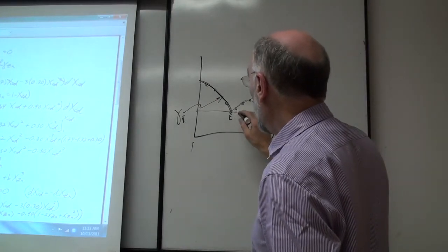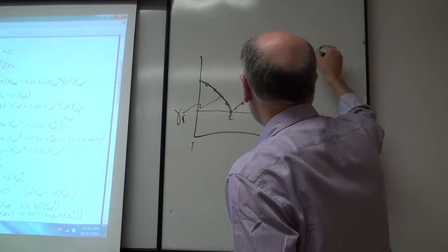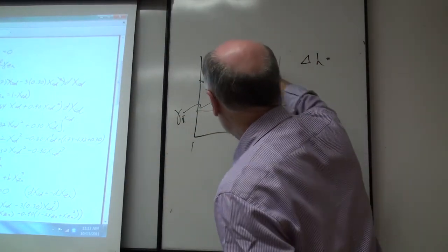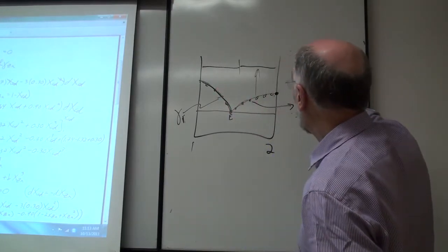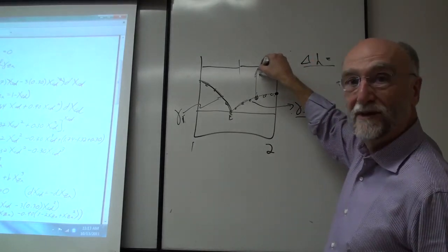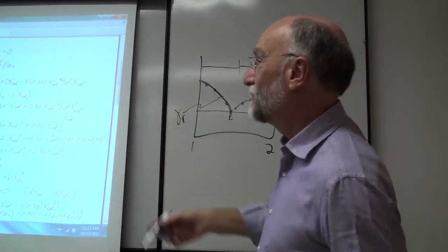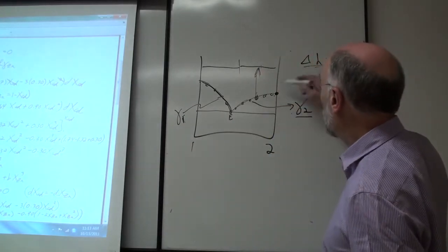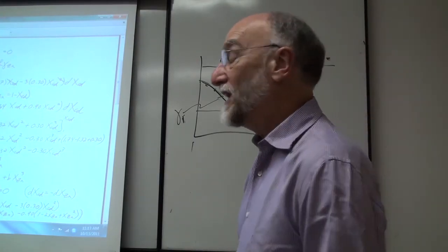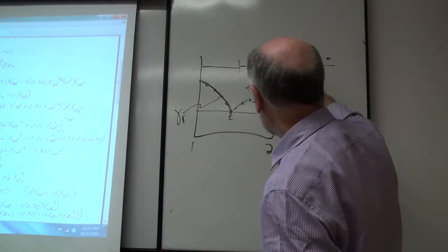Now, you can't integrate the Gibbs-Duhem equation strictly because you don't have a constant of integration. It's not isothermal, but if we know the heat of mixing, then as we did in the problem, I think 13.3 or something, you can integrate these up using the delta H. You can take the log gamma 2 at this temperature and move up to log gamma 2, right? Okay, as we did, I think it was a bismuth cadmium system, 13.3. We had log gamma 2 from the liquidus, we knew the partial heat, so you could get log gamma 2 at a higher temperature. Or you could assume, for example, that the excess entropy is 0. You're making some sort of assumption, anyway, to render your gamma 2's isothermal.